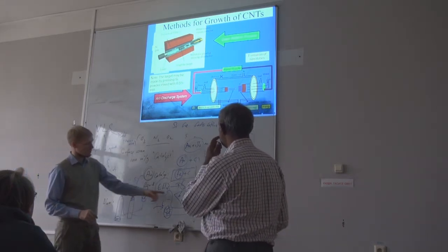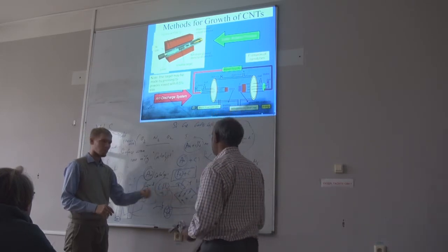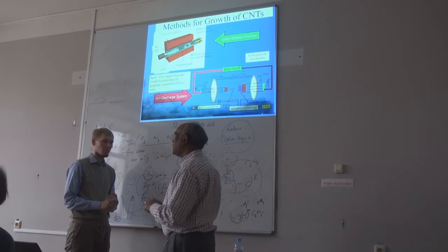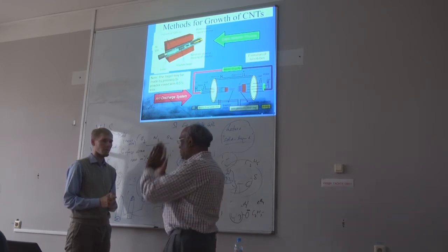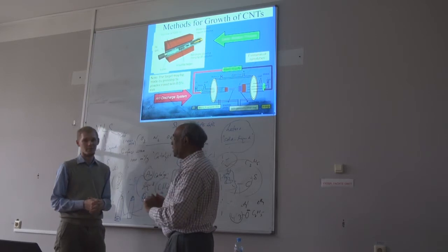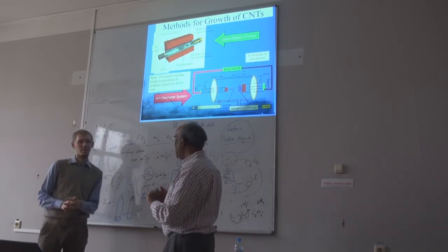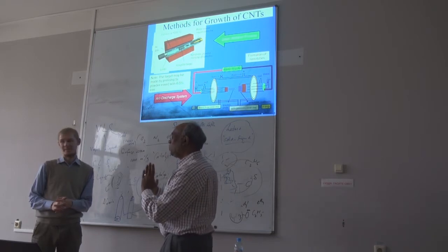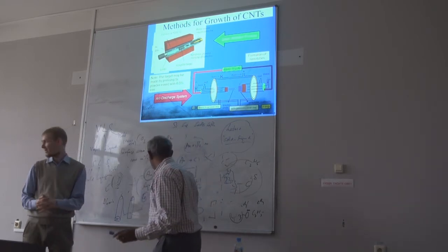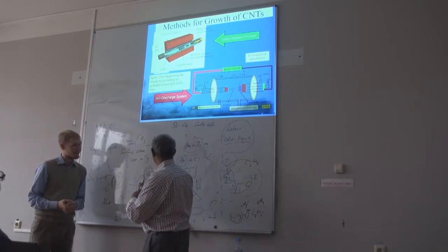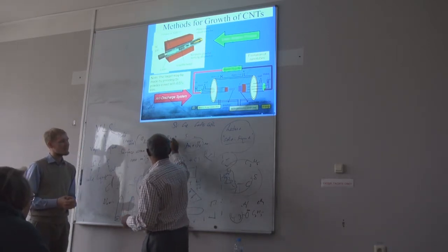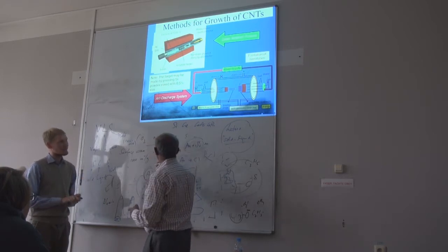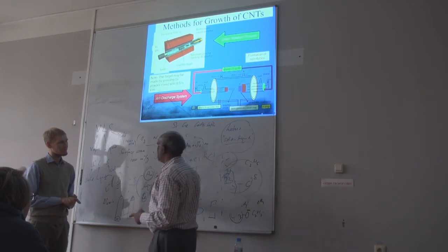You know, it's not vertical. No. But you can grow vertically. There's something called super growth. They are called nanotube forests. That's something people still don't understand. The technique is to introduce a little bit of water. What happens is, when you grow this, the iron and carbon are coming together, right? Eventually they will make iron carbide. So this is a bad catalyst.